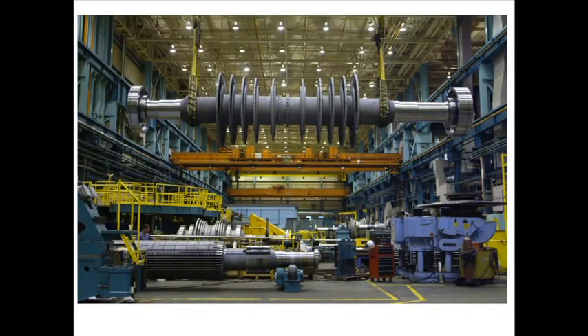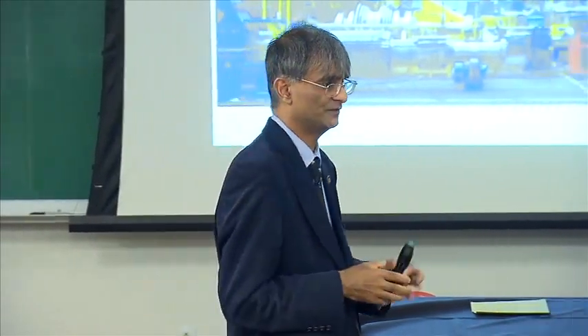Now, going back to this problem of the steam turbine, in order to get greater thermodynamic efficiency, we need to raise the steam temperature to beyond 600 degrees centigrade, even 700 degrees centigrade. There is no ferritic steel capable. So we tried very hard to develop a ferritic steel. There were major international programs to do this. They really haven't been successful.